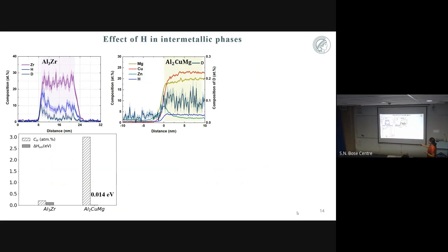Yes, the Y-axis is representing both of them. So these are the composition profiles we have obtained from the experiment. In aluminium zirconium, however, contrary to what we have got, you see aluminium zirconium and aluminium copper magnesium. So, let us focus on this blue hydrogen curve or the deuterium one. It is much more in aluminium zirconium. The hydrogen is trapped much more there, the content of hydrogen, than what is trapped here.